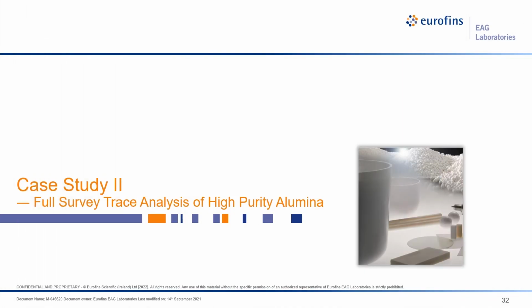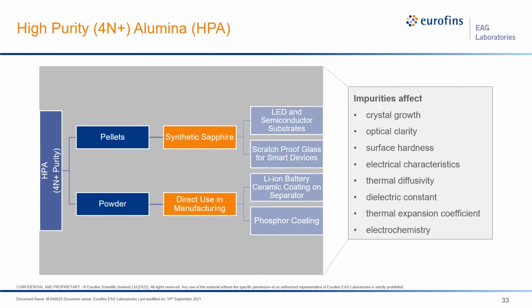The second case study relates to high purity alumina. High purity alumina is manufactured in two formats, pellets or powder. They can be used either to make synthetic sapphires or directly used in manufacturing processes. In terms of sapphire, they're used for LED and semiconductor substrates, and also for making scratch-proof glass for smart devices. In terms of direct usage, they are used as ceramic coatings on separators of lithium-ion batteries, or phosphor coatings. In all those high purity aluminas, impurities affect the crystal growth process, optical clarity, surface hardness, electrical characteristics in semiconductor materials, thermal diffusivity, dielectric constant, thermal expansion coefficient, as well as electrochemistry behaviors. So there is a need for full survey to account for all those impurity atoms.